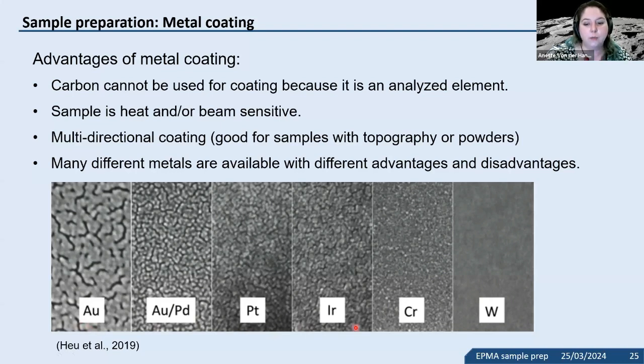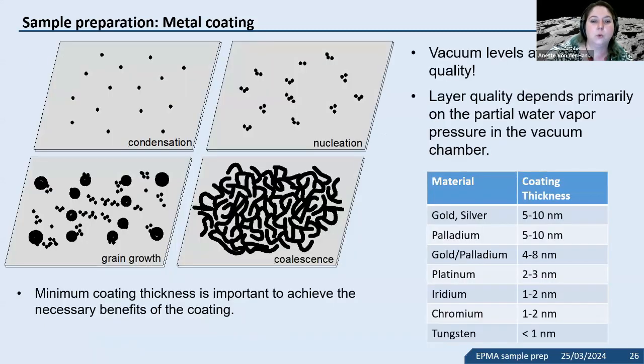But then there are a whole range of materials, and there's a really nice paper in Microscopy Today that goes into the pros and cons of the different types. An important part of the coating process is that the vacuum level affects the quality, and that's true for all kinds of materials. And specifically with a metal coating, there are minimum coating thicknesses that you need to follow in order to actually get a conductive coating. Because in the first step of metal coating, you just have condensation, then you have nucleation, grain growth, and only in the coalescence step, you actually get a continuous film. And so different materials have different minimum coating thicknesses, and that can then be another thing to follow, where if you want to have a thin coating, you can't use certain materials, or other materials are more ideal for that.